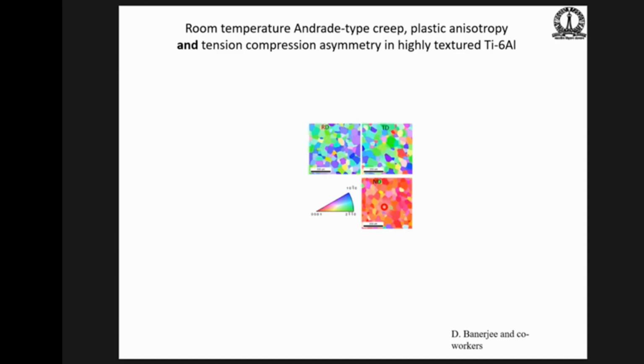Now, titanium is complicated for many reasons. Apart from creeping at room temperature, it also has tension compression asymmetry. And we didn't want to deal with that right away. And of course, it has this decaying creep. You never reach steady state. So we began to analyze this problem because now we had to do some bit of mathematical analysis along the rolling direction, where we expected things to be symmetric in tension and compression.